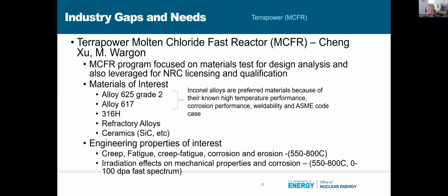But some other materials are 316H, most probably with a coating, or maybe even in the future, they can go to even refractory alloys or ceramics. And so there's, once again, areas where I think this program could really help out. But there's a lot of engineering properties that they need for these materials, especially if they're running at high temperature. You can see they want to go from 550 up to 800 degrees C, so quite high temperature. And at those temperatures, creep, fatigue, corrosion, and erosion are all areas where they really need information on those materials. And then on top of that, they need radiation effects on their mechanical properties at those temperatures. And that's in the sort of 0 to 100 dpa fast spectrum area.